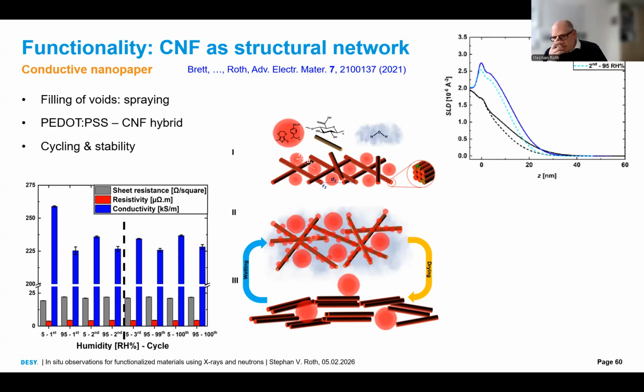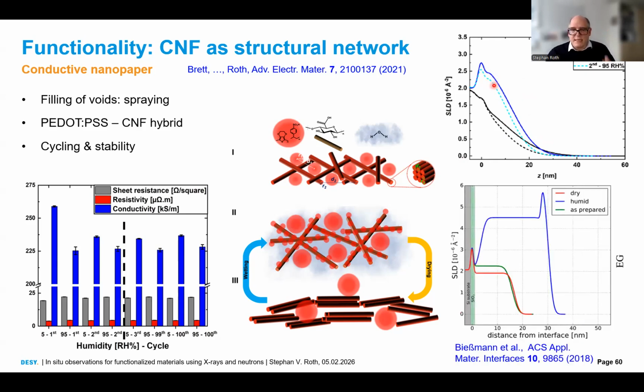And even more important, what we did not know at that time: when you take these PEDOT:PSS CNF films and you humidify them, they do not swell. So we measured with XRR the vertical size of our hybrid films, and they stay the same. If we would use pure PEDOT:PSS, it would swell. So what we have here is that we don't observe swelling, but this CNF is like a structural network. It can slightly rearrange, but it doesn't swell. And this is very important. This gives you a stability of your electrode.